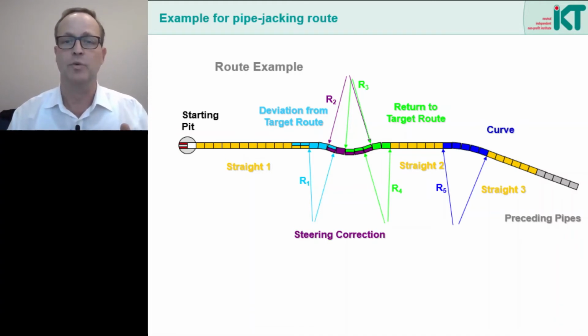This sample route was a first important result of our research work. And this route was the basis for many laboratory simulations on a scale of 1:1. And one finding was particularly important for the simulation. We can see in the picture that all situations can be simulated well with just 5 pipes. The straight line, the steering correction and also the planned curve, all this can be ideally simulated with 5 pipes. And that is how we did the large-scale tests at my institute, the IKT.